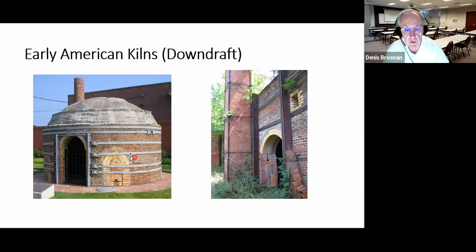Of course, to restrain the kiln from the thermal expansion, there were these metal straps or bands around the outside of the kiln, trying to hold the bricks, the fire bricks on the outside in compression so that they would not tend to spall. Of course, there's a dome or a crown on top of this kiln that's round. So the air moved upward and came down in a downdraft kiln, still solid fuel fired before the time of electricity when we had fans to move air around.